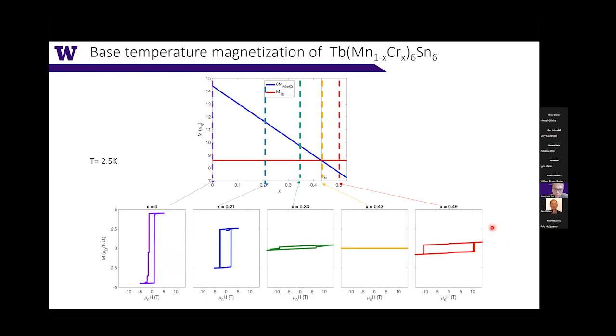So this is exactly what we did. We have grown a series of chromium doped terbium manganese six tin six all the way from 0 to the doping range of 0.5. So almost half of the manganese is substituted by the chromium. So this is also beyond the point where we expected to have this reversal of the magnetization. So here I'm showing you the base temperature magnetization versus field plot. In the parent compound, you have this nice hysteresis loop, and the saturated magnetization has the value corresponding to what you would expect from 6 manganese and 1 terbium.